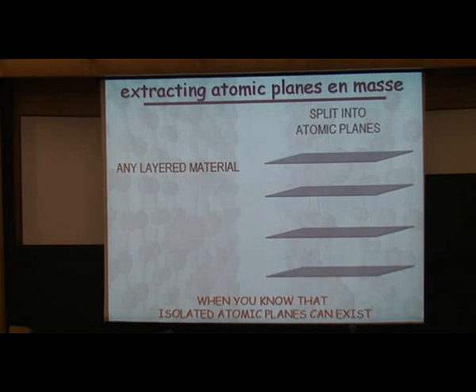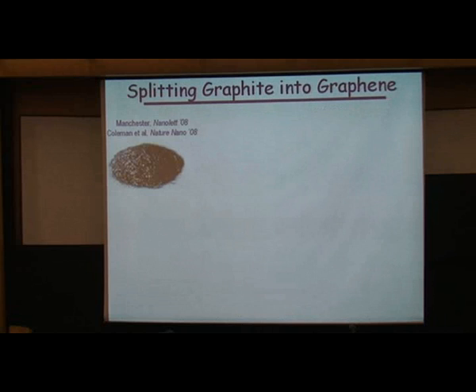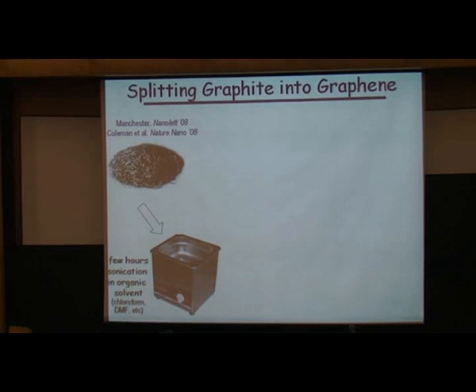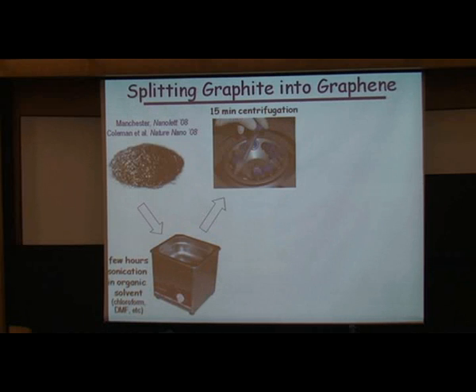A couple of years later, after extracting, we thought, why are we wasting material? Let's take graphite and extract not a single flake, but plenty of those. What you have to do is use trivial equipment that experimentalists know exists practically in any lab. You have ultrasonic baths, you sonicate graphite in these baths for a few hours, then centrifuge, and what do you end up with? You end up with a solution or suspension of floating, mostly monolayer graphite flakes, which is the definition of graphene, mostly single layers. It's stable, it's a solution of graphene, if you wish.